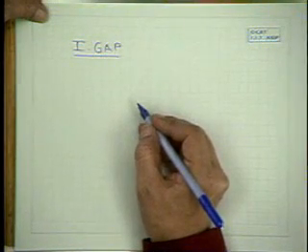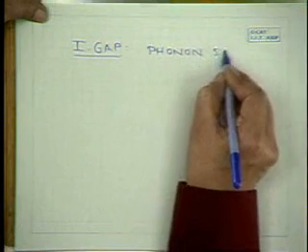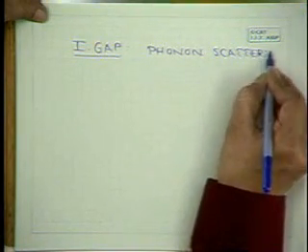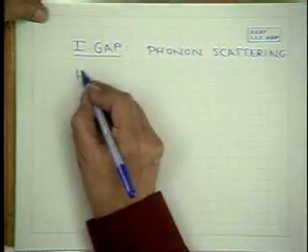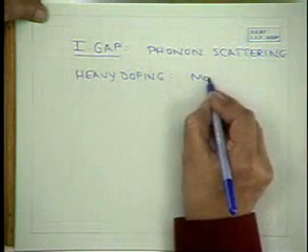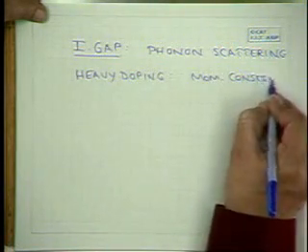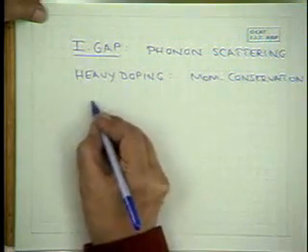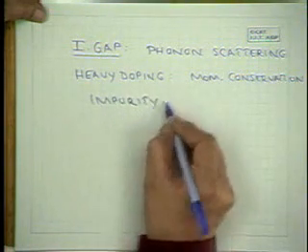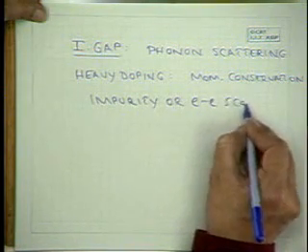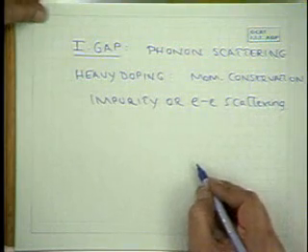It is found that as the edge shifts for an indirect bandgap semiconductor, where normally phonon scattering is involved. As we have seen, optical absorption involves phonons. But for heavy doping, you can get momentum conservation from either impurity scattering or electron-electron scattering. So phonons need not be involved.